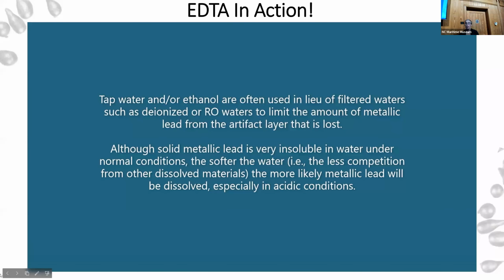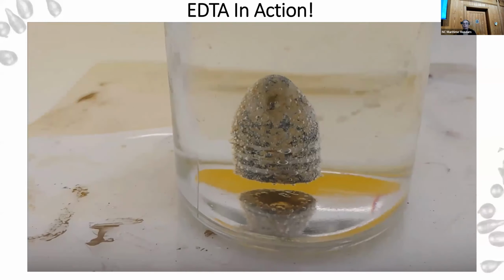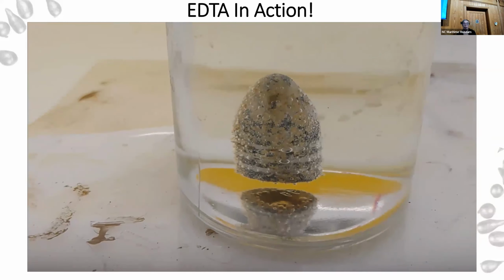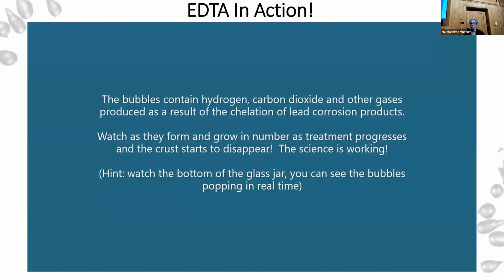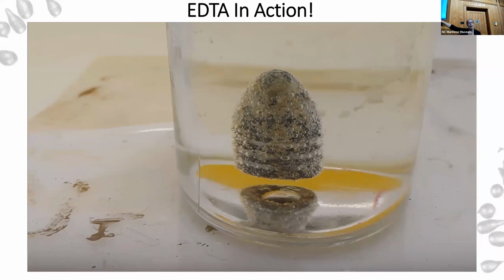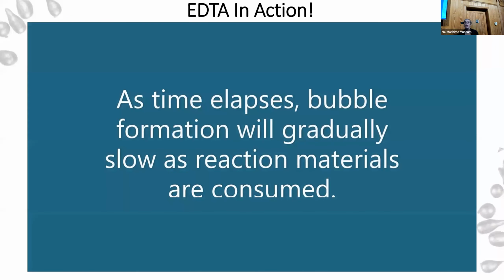All right, so we have put our mini ball into a solution of EDTA. It is a 5% solution, and we're going to leave it in there for about 2 hours. What I want you to pay attention to is the evolution of those bubbles, that hydrogen, that carbon dioxide, and other gases which are forming on the surface. As you can see, the more chemistry that is happening, the more bubbles you're going to get. Over time, as this crust slowly starts to dissolve and deteriorate, those bubbles will start to dissipate and you won't get as many.